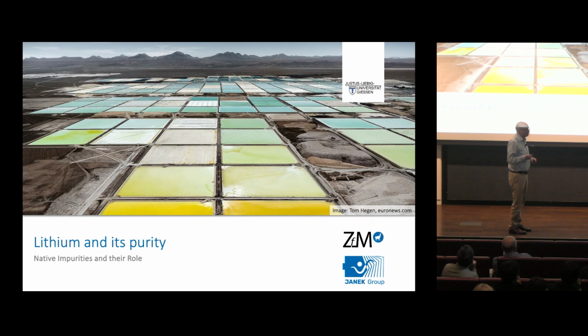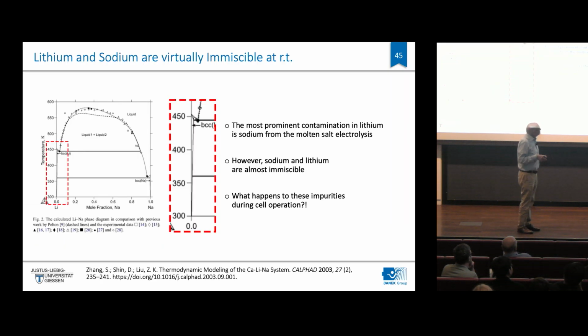Okay, final point, and then I think I really stressed my time: we found out during that research that the purity of our alkaline metals really is critical. You know that these are big salt brines in South America where lithium is being harvested. And now if you look into what is the quality of today's lithium, if you buy lithium metal, it's pretty dirty. You often will find impurities of 1 or even 2%, mostly alkaline metals, sodium, for example. If you look into the phase diagram of lithium-sodium, you'll find lithium and sodium are virtually immiscible. But you will find impurity contents of 1 or 2%.